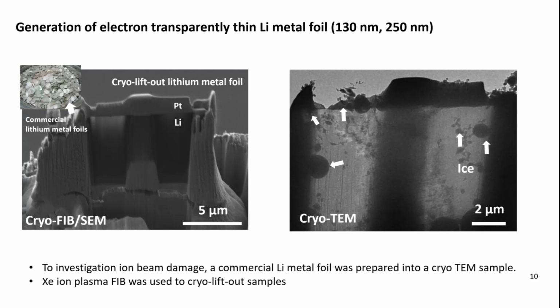In the cryo-biologist workflow, they have a pre-tilt shuttle, so they have their own anti-contaminator to protect their sample from this. So if you really worry about this ice condensation for your analysis, you can also perform some on-grid TEM sample preparation, which is a little bit different from the cryo lift-out procedure. But yeah, this is where ice condensation usually happens.